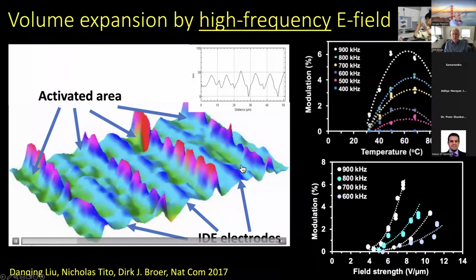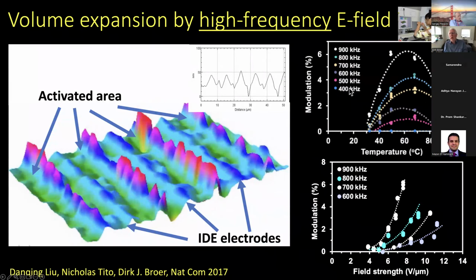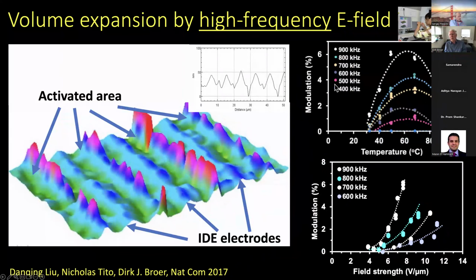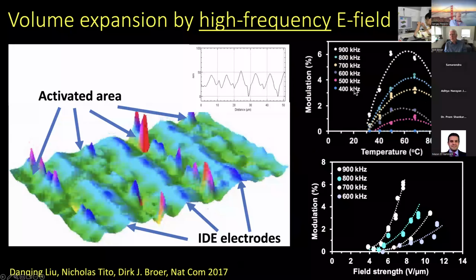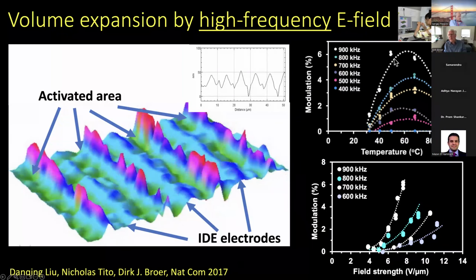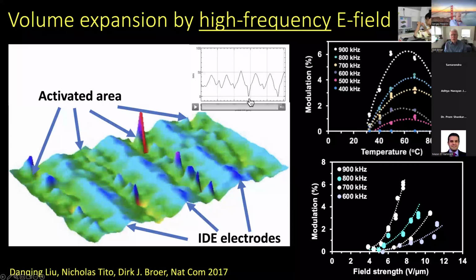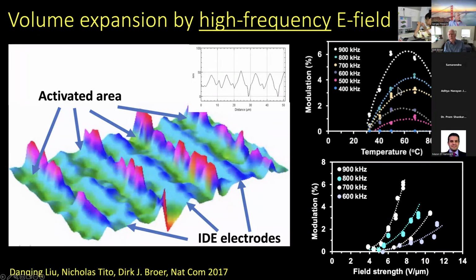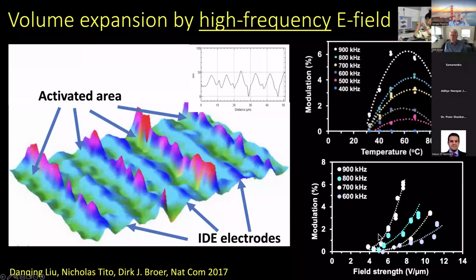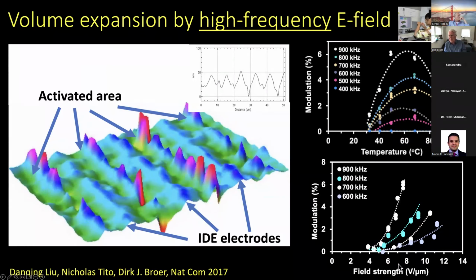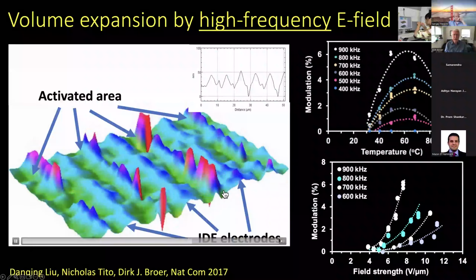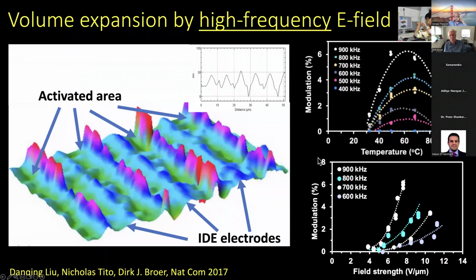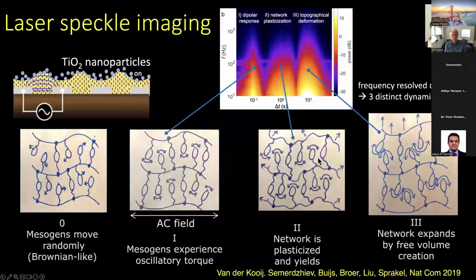The frequency that you need for this is relatively high, so the system starts to work only above 400 kilohertz. I come in a minute to the explanation why. So you need to drive the system at high frequency, almost at radio frequency, and of course it scales also with the field strength that you apply. Typically we are applying 40 to 60 volts between the two electrodes.